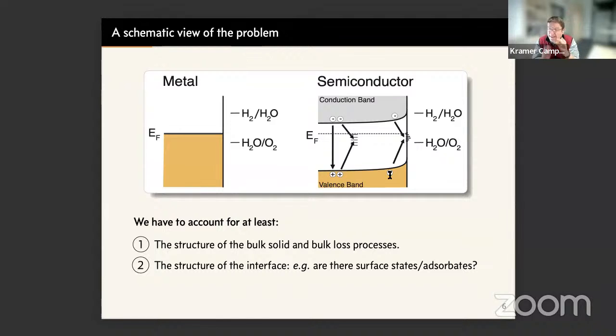Okay, so this schematic picture should suggest to you that if we want to understand what's going on, we will need at least to understand the electronic structure of the bulk solid and any bulk loss processes. So this mostly matters in the case of the semiconductor. This is what I have tried to show here, right? So to drive chemistry, we need to create electrons or holes at the interface. But the problem, of course, is that electrons can relax back into the valence band, and then you lose the electron in the hole, or they can recombine at bulk defects and not participate in the chemistry, right? So we need to understand these loss processes if we want to understand what makes particular semiconductor materials efficient.